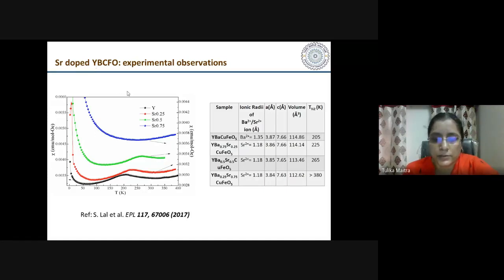We also did some calculations for the strontium doped compound, for which some experiments were done recently by the IIT Mandi group, S. Lal and others, where they saw that if you dope strontium at the barium site, then the incommensurate phase transition temperature increases with doping. Okay, from 205, they can raise it up to 380 Kelvin. Because this incommensurate phase, if it is associated with a finite polarization, then if this transition temperature can be raised, this becomes a very good thing for application purposes. If the transition temperature is high and the compound contains polarization, then you can have multiferroicity at room temperature, which is very good for application purposes.